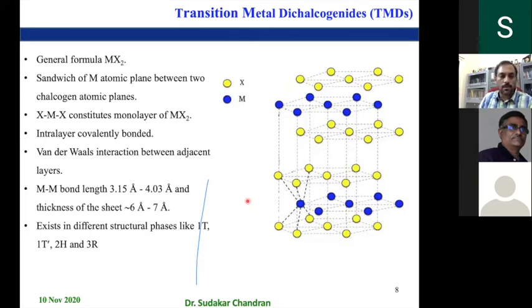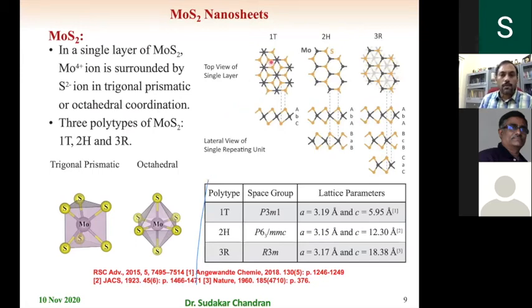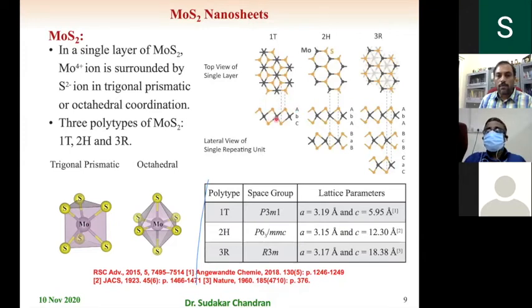So molybdenum disulfide or transition metal dichalcogenides exist in various structural forms. 1T, 1T prime, 2H, and 3R are the different phases known. They differ in the way the molybdenum and sulfur layers are arranged. For example, if you take the 1T phase, the top sulfur layer is A, in between molybdenum is B, and the bottommost sulfur is C. So it's like ABC stacking, as you might have studied in cubic close packing. ABC stacking is what the 1T phase has. Whereas the 2H phase has ABA, BAB stacking, which repeats afterwards. And there is also another phase called 3R. It has ABA, BCB, CAC, and then it repeats. So they differ in the way the layers are stacked.